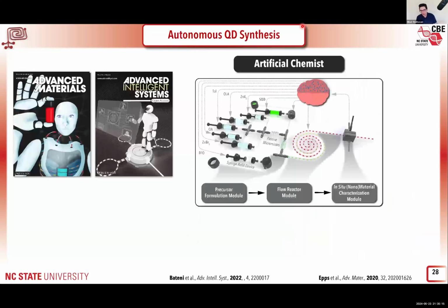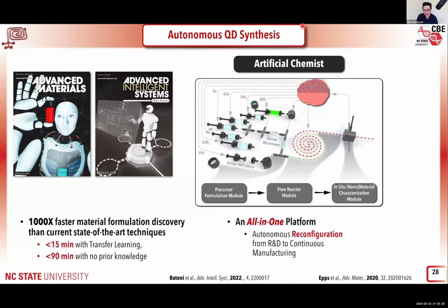So after the fine-tuning of our AI agent, we integrated that with our automated hardware, automated flow reactor, to do this autonomous closed-loop synthesis of these quantum dots. This was like 4.5, 5 years ago, and we already showed that with the first generation of autonomous fluidic lab, we call it artificial chemist, we could autonomously discover the synthetic route of any target emission color of quantum dots within only 90 minutes if you treat the system as a black box.